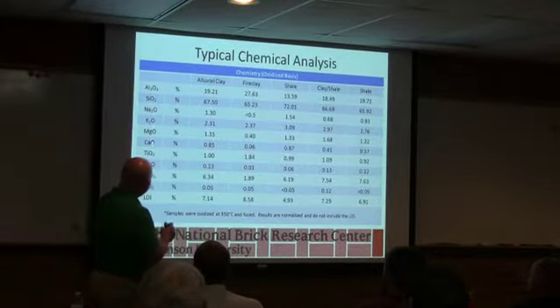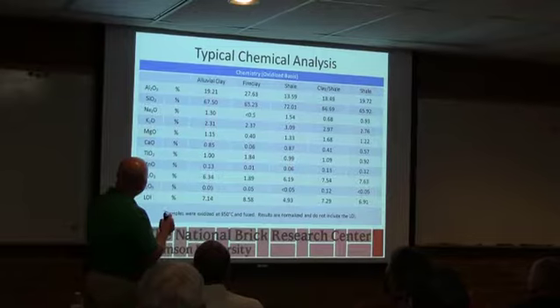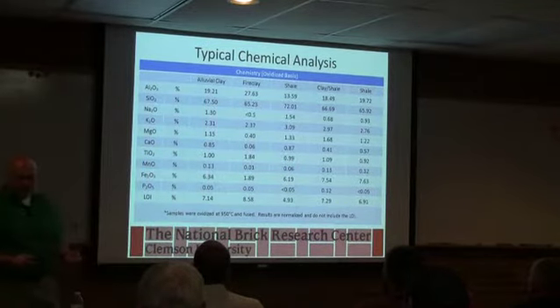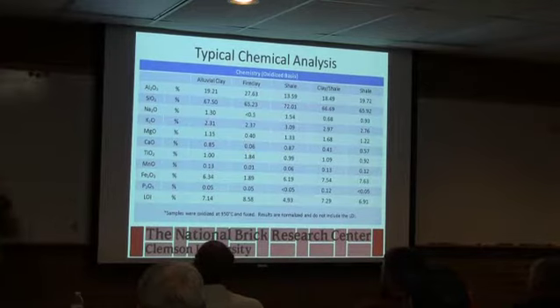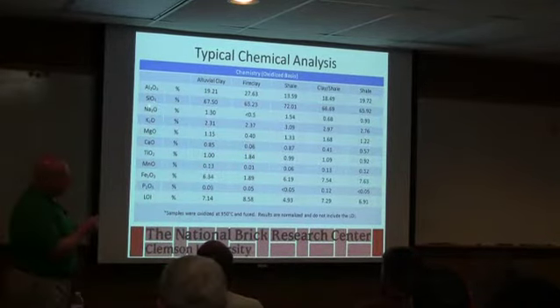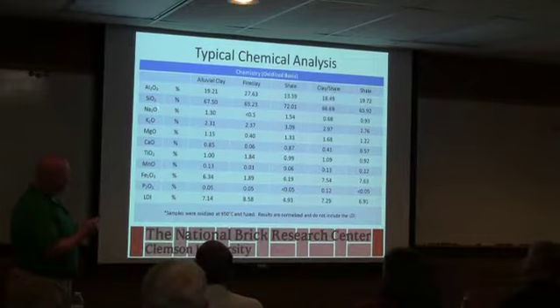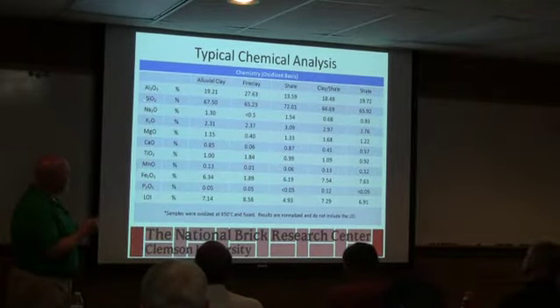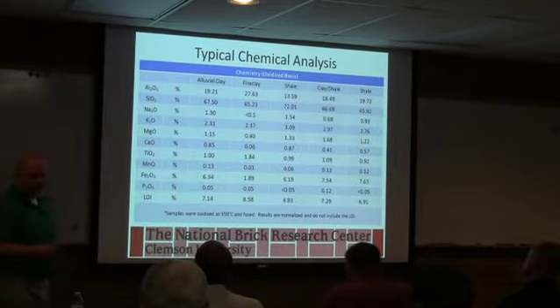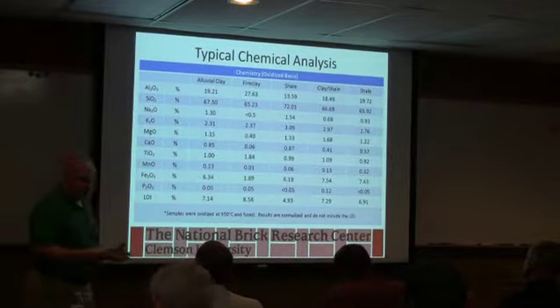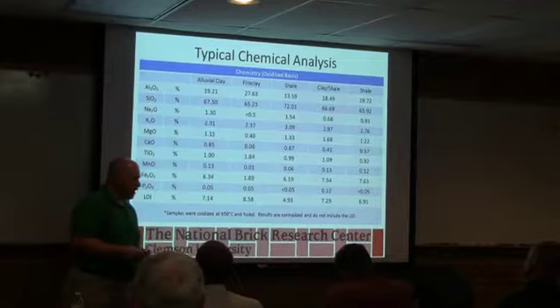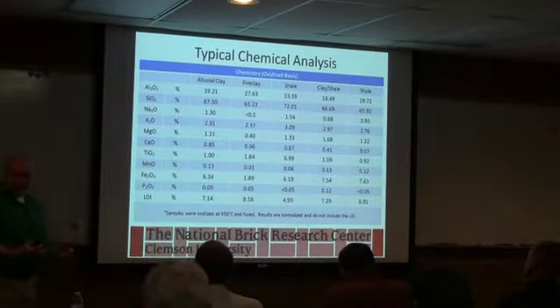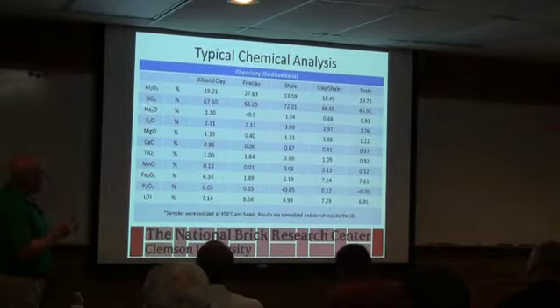But when we do a chemical analysis, we are really just measuring like the aluminum, the silicon, the sodium, and by default we're assuming they're oxides. Okay, that's just the convention on how this works. So we're not actually measuring SiO2, and I mention that specifically because that causes a lot of confusion. People see that number and they think, well, I've got 67% quartz. Now, you've got 67% silica somehow distributed in your material. It could be in mica, it could be as part of the clay mineral. Okay, so the silica can exist in a lot of forms. It's not necessarily quartz, and we'll talk about quartz as we go along.